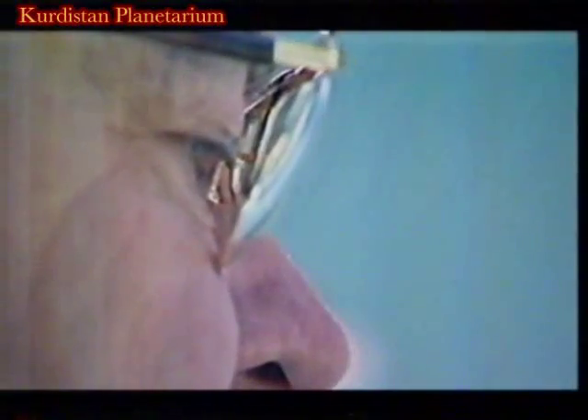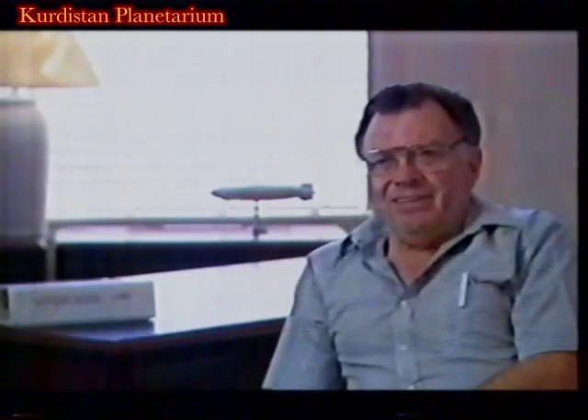Examining the fabric first under an electron microscope, then using infrared spectroscopy, he was able to determine the precise mix of chemicals used in the doping compound. He found that iron oxide and powdered aluminium were all part of the doping mixture. Being associated with the space shuttle activity, Bain knew that powdered aluminium was the fuel used on the boosters — and he thought, what a bad combination.